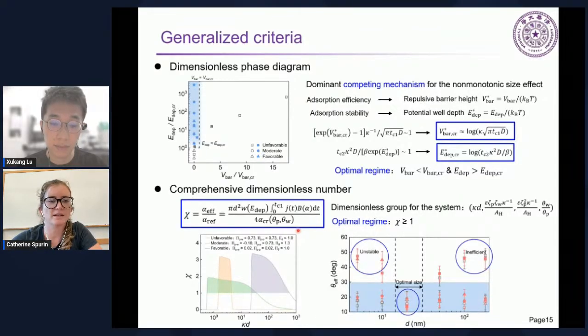Like if you have some uncertainty in that, would you likely cross into a different regime? You mean when because of the advancing and receding, it will change significantly or not? So I think it is actually not that sensitive to wettability conditions, because the key factor here is probably the adsorption kinetics. And of course, wettability will change the quantitative results, but the general trend, it plays a minor effect. So I think advancing or receding will not influence it that significantly.